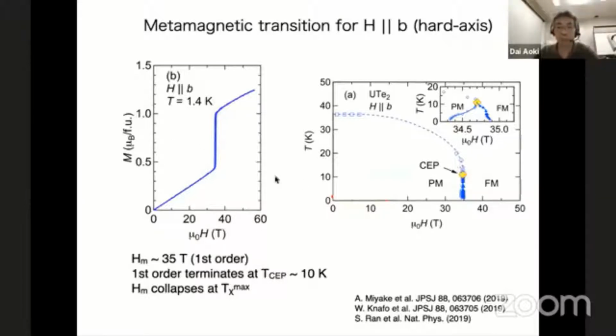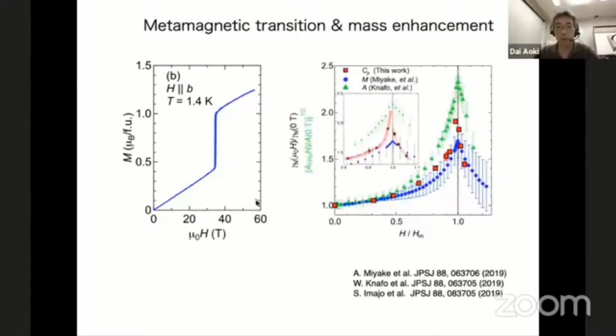And at this metamagnetic transition, we have a sharp peak in the specific heat. Here it shows the specific heat gamma scaled with the normal zero-field gamma value, or the effective mass, from the A coefficient of resistivity, or the gamma value detected by the magnetization using the Maxwell relation. You can see a sharp peak, and this is important for the superconductivity. I will show you later.